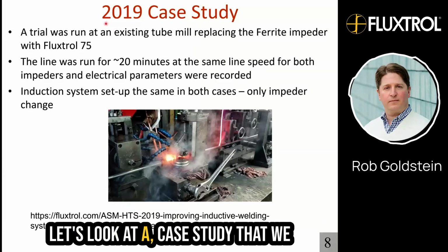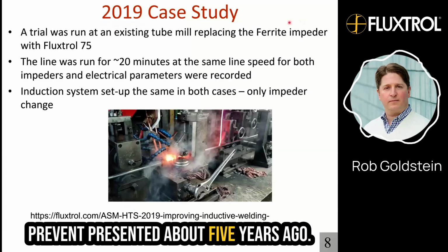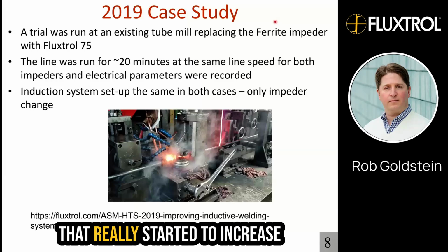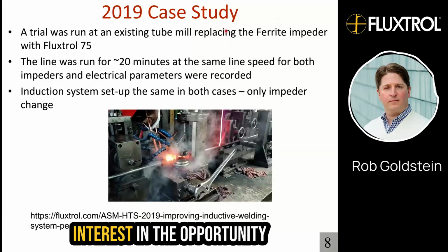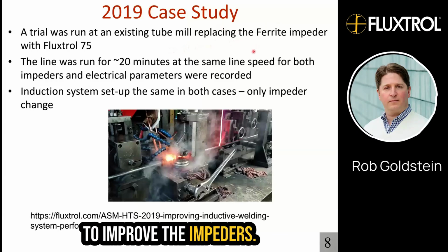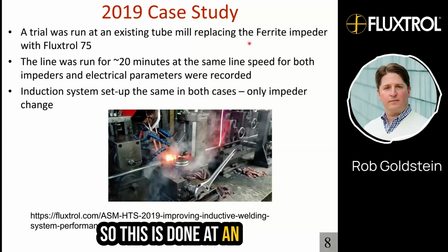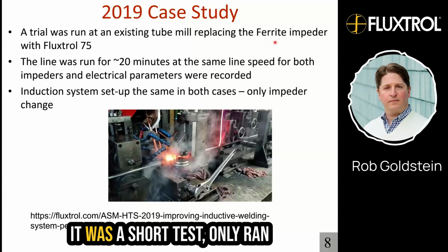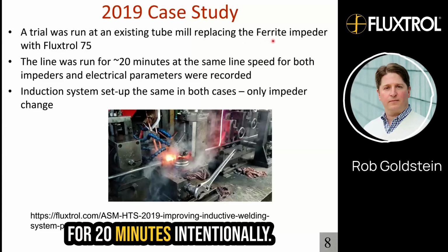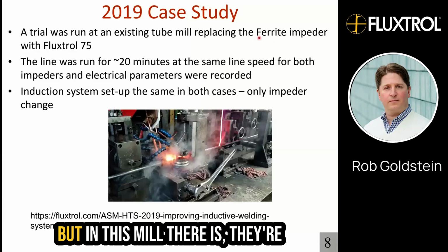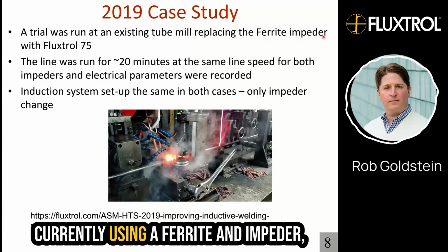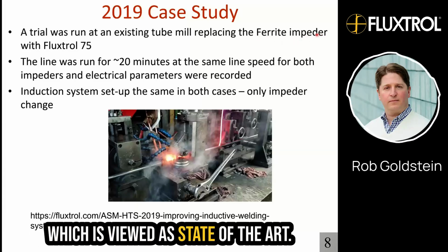Let's look at a case study that we presented about 5 years ago that really started to increase interest in the opportunity to improve the impeders. So this is done at an industrial tube mill. It was a short test, it only ran for 20 minutes intentionally. But in this mill, they're currently using a ferrite impeder, which is viewed as state-of-the-art.